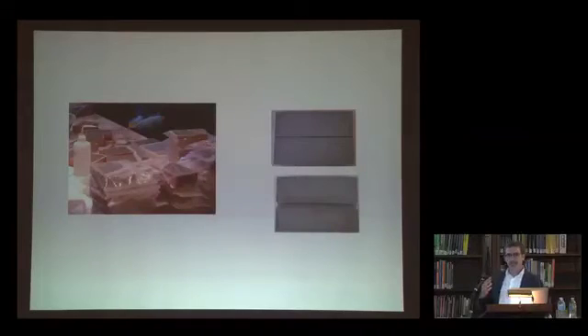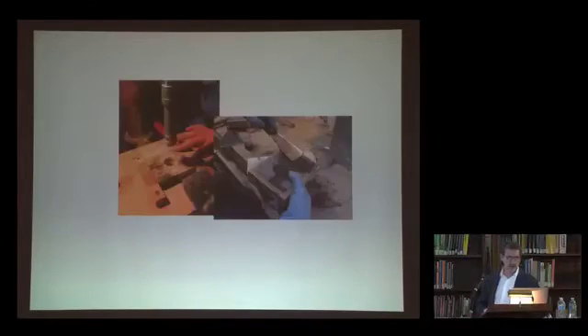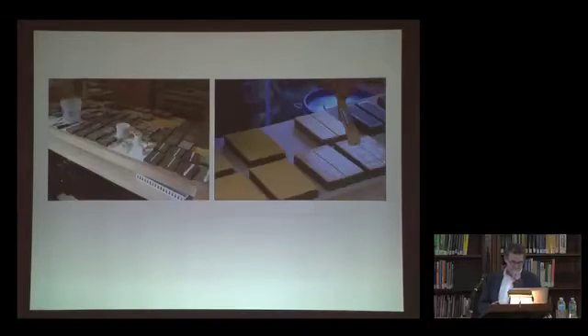We tried to think about how we could mimic the different cracks and areas that required patching to also include that in the program. So here we tried to create a smaller crack, here a little bit of a larger crack. We also drilled holes in some of these samples and through the cracks so that we could put patching materials in there. And here on the right, you can see the patching material being applied. On the left, now some of the crack filling, expandable crack filling materials are being installed. And after that's done, some of the elastomeric coatings are being applied.